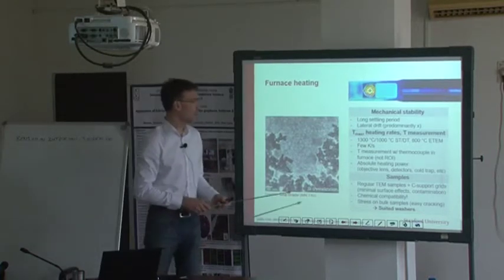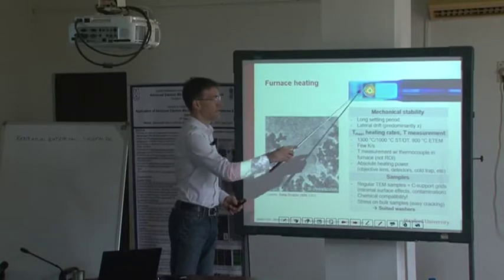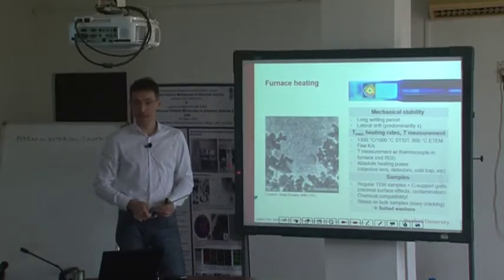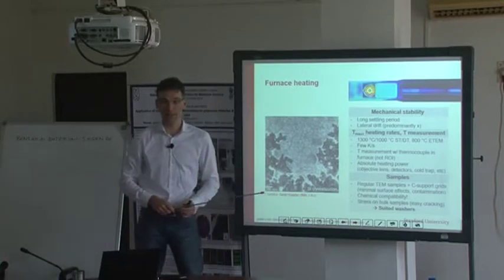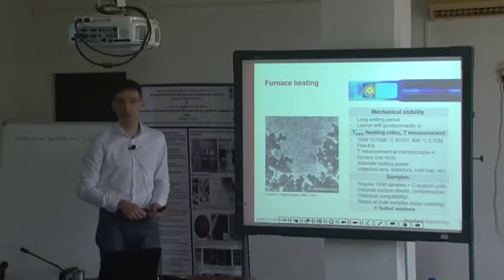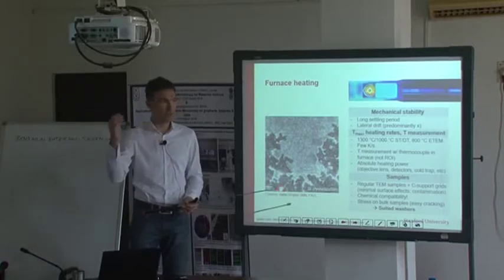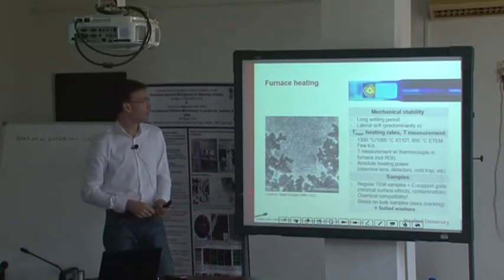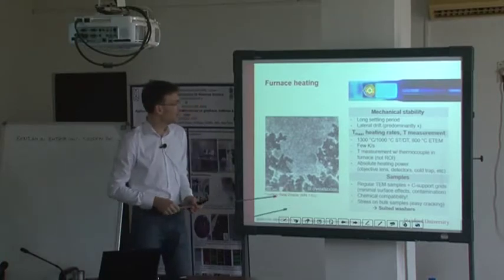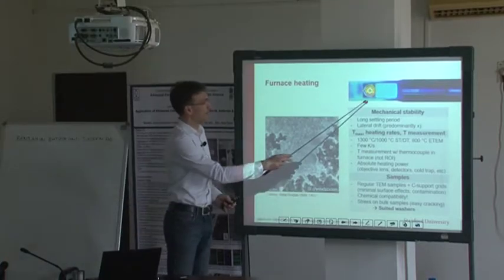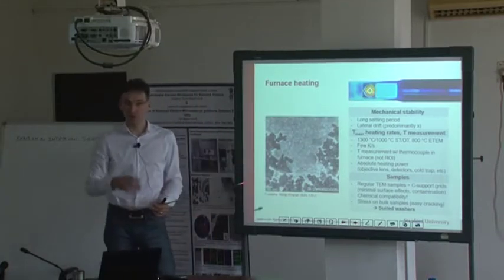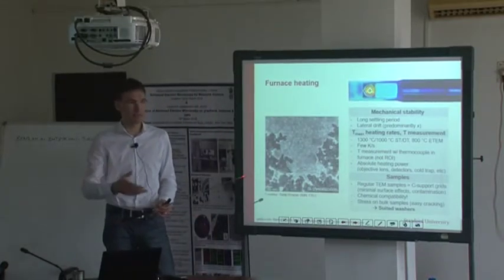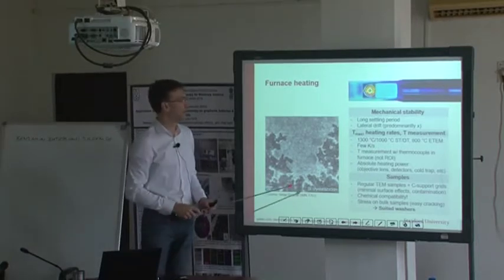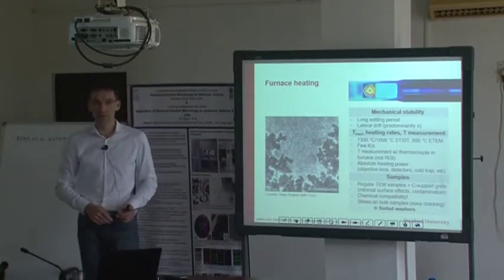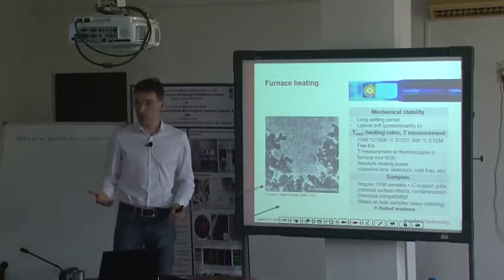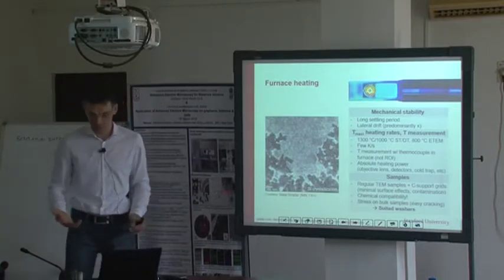Okay? There's one big disadvantage here, which is the evolving heat loss at higher temperatures. And if you want to conduct, for instance, any chemical analysis with your EDS detector, you will run into trouble with infrared light on your EDS detector. So this is a big disadvantage. You cannot do chemical analysis at high temperatures. Another disadvantage is that you might end up with a strong drift of your sample, because whenever you heat, you introduce stresses, and by that, drift might occur. People are interested in atomic resolution imaging, so with this, you can hardly realize atomic resolution imaging.